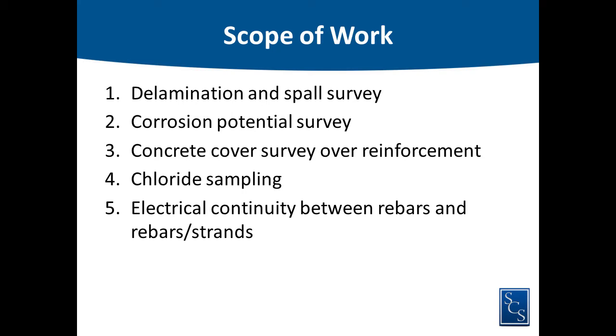Some NDT tools may not truly reflect whether it's a delamination or simply a crack. We've used infrared cameras, but beyond three inches it's difficult — particularly if the structure is sitting in the water, where water acts as a heat sink. Chloride sampling is absolutely essential. You have to get an idea of how much chloride you have and how deep it is, and that will tell you your options. Continuity is also essential — if you're going to do any mitigation to address corrosion, you want to make sure your steel is in one piece. If steel pieces are all discontinuous and you apply current, that current only goes to pieces connected to the anode. Pieces that are not connected may actually corrode — that's the reason you want to know that and fix it.